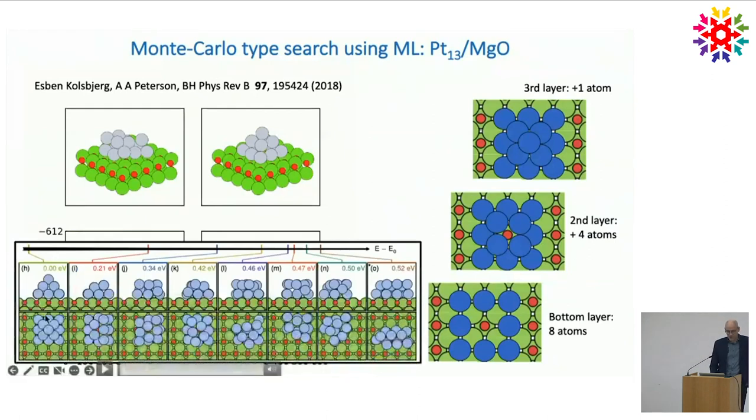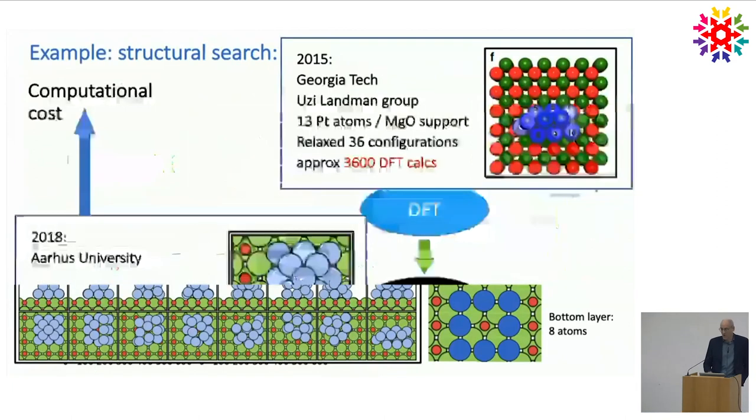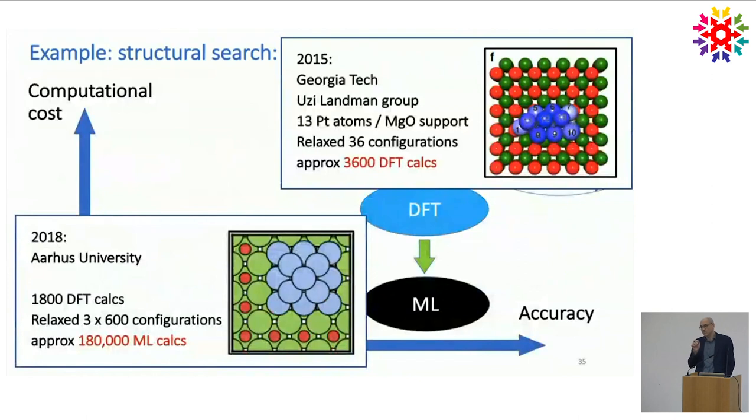And we found a whole lot of other structures. Another six structures were also stable that were all more energy-favorable than the structure found in the previous search. So it just shows you why we need to do the global optimization, and why we need to do it automatically with the basin hopping, just let it run, and why we need orders of magnitude more configurations than you can cover if you do this by hand and at the full DFT level.